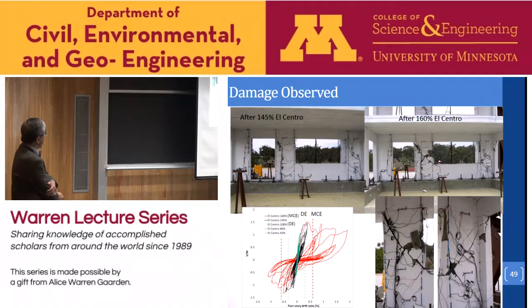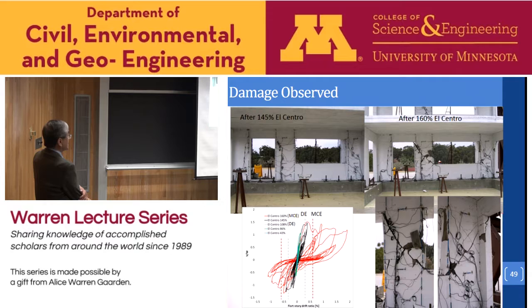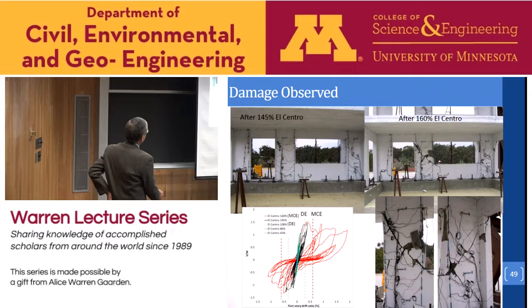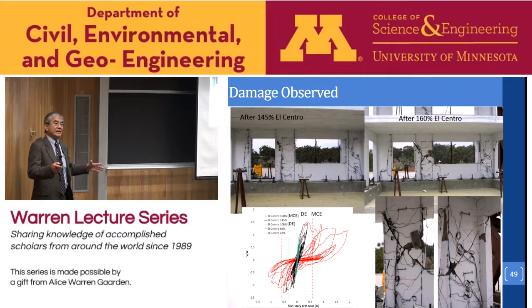Now this shows some pictures of the damaged structures and the base shear versus the drift ratio at the first story. You can see that the structure performed as expected at the design earthquake; the drift level satisfied the design limit. However, at the MCE level, the structure drifted way more than that. That could be attributed to the damage suffered by the structure prior to this run.